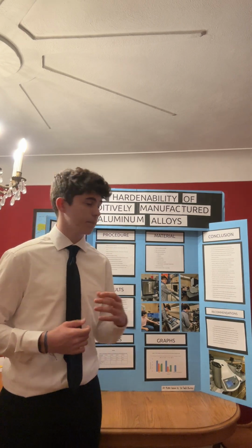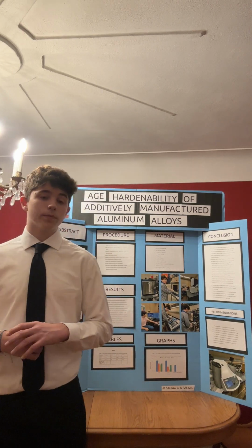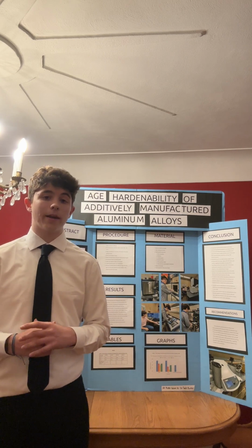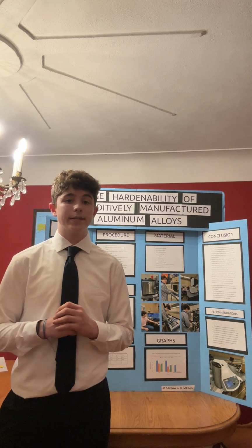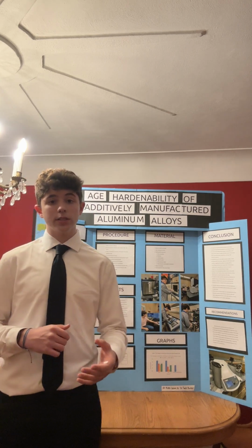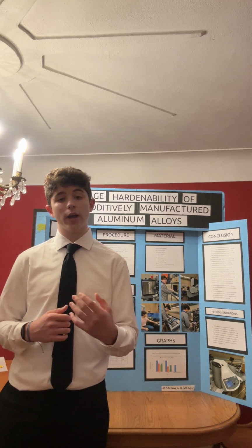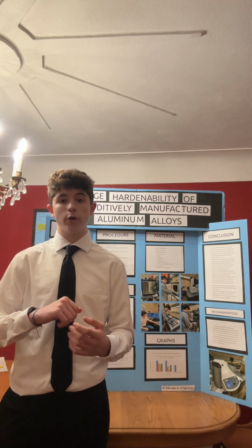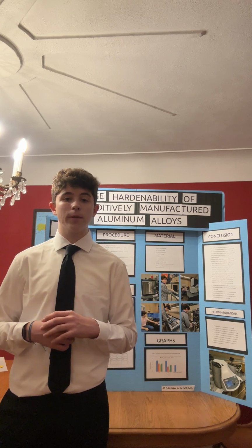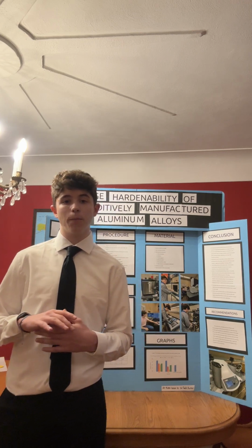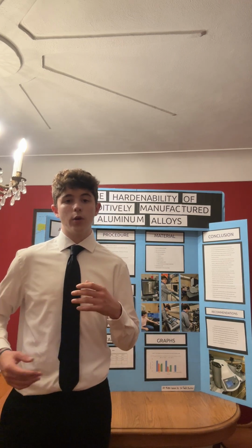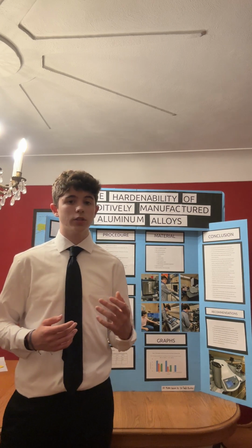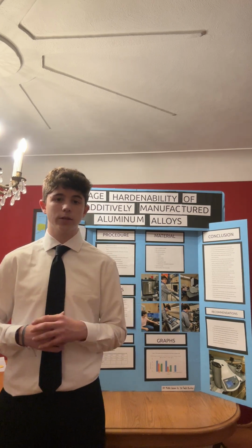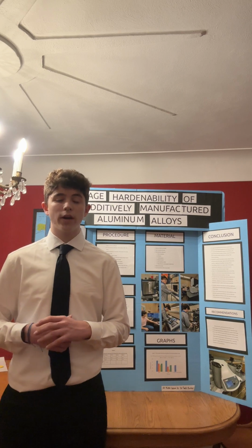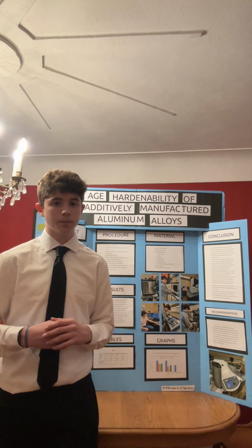project has concluded. The procedure was first to obtain the aluminum alloys, which was done on base at a lab. How this works is they put the metal as a powder on, and a laser goes over it, which melts it and then rapidly cools so that it has a layer of metal. You do this layer by layer, and you get your structure. Each of these samples was a cube 1 inch by 1 inch by 1 inch.